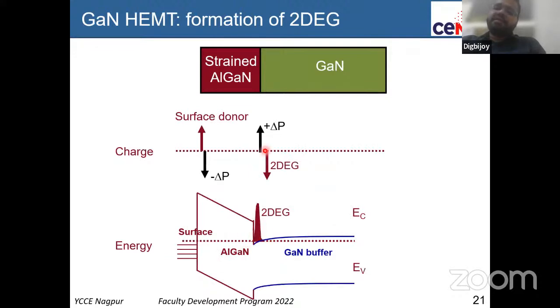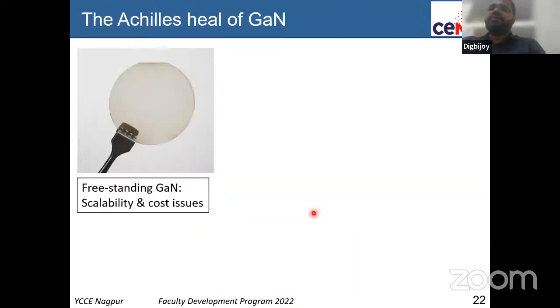And at this interface, there is a two-dimensional electron gas that forms. It's a very high density of carriers, as I told you. And this is unique to this structure because you can get it without any doping also. It's a very, very interesting property that without doping, you're able to get a 2D electron gas.